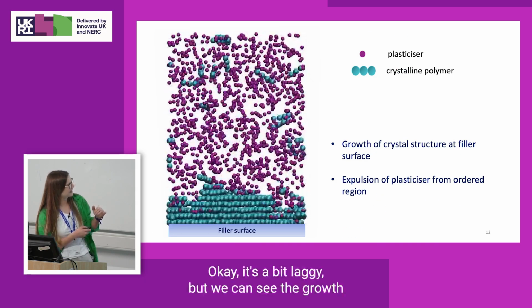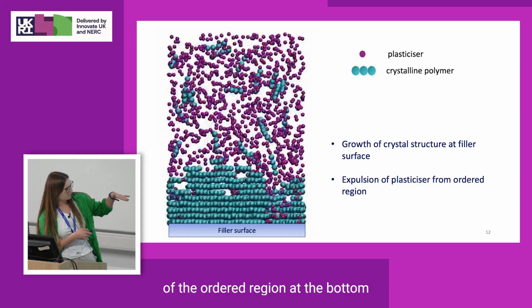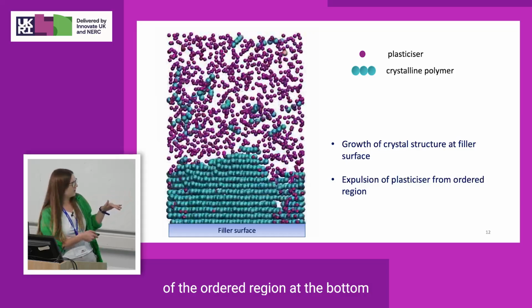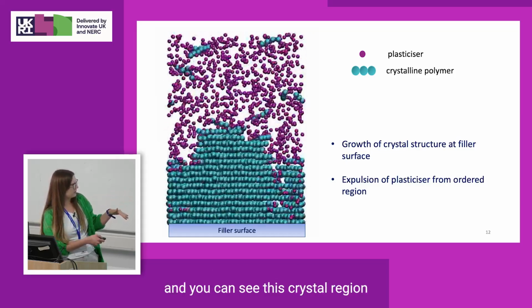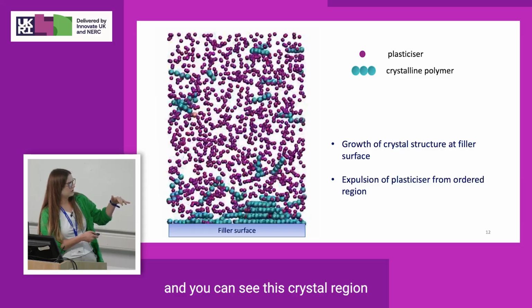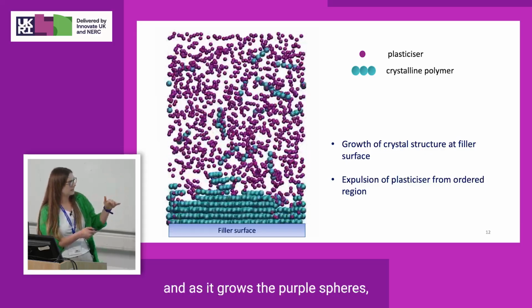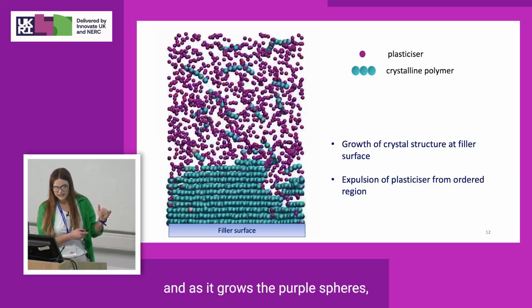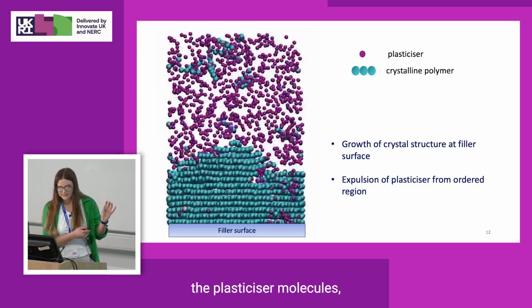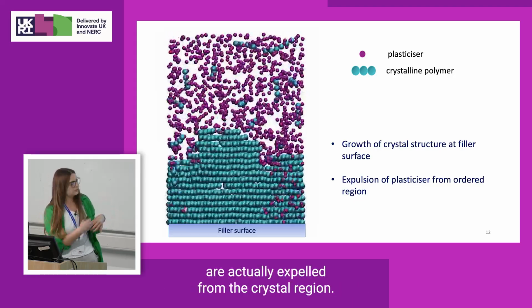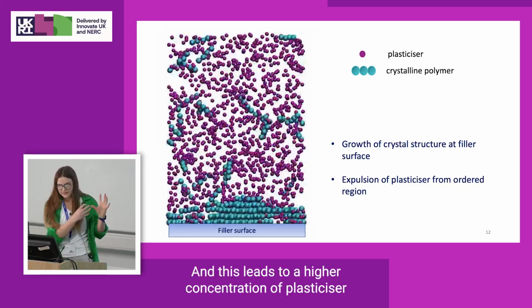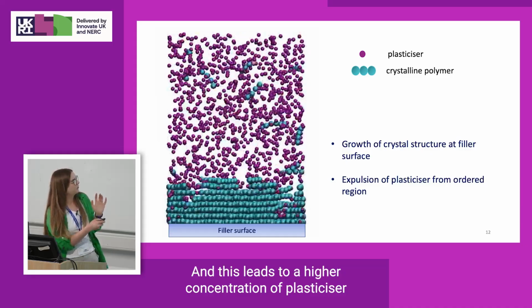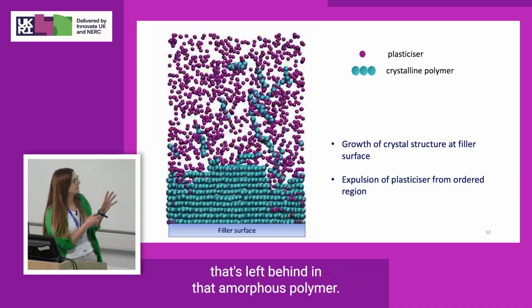Hopefully it plays. Okay, it's a bit laggy, but we can see the growth of the ordered region at the bottom. So this is our filler surface at the bottom, and you can see this crystal region grows up from the bottom, and as it grows, the purple spheres, the plasticizer molecules, are actually expelled from the crystal region, and this leads to a higher concentration of plasticizer that's left behind in the amorphous polymer.